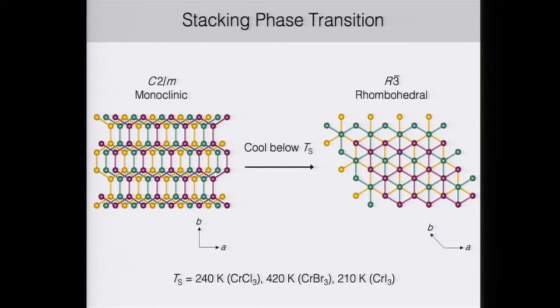They all undergo a stacking phase transition in which the bonds between the chromium and halides don't really change, but the stacking between adjacent layers shifts dramatically. Here I'm omitting the halides and only showing the chromium honeycomb structures for 3 adjacent layers. You can see that at high temperatures, there's this monoclinic stacking where the layers shift along the a-axis. Then below the structural transition, which varies depending on the material, it adopts this rhombohedral ABC-type stacking instead.